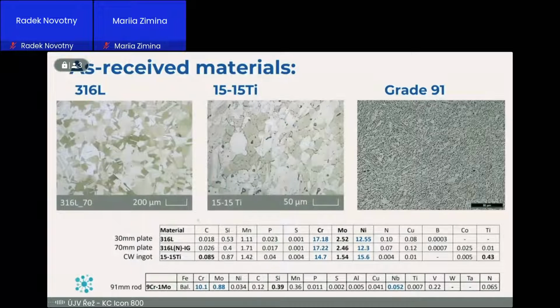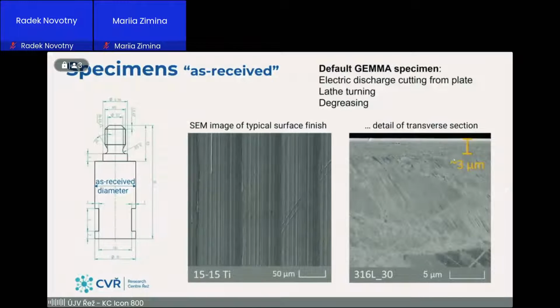There is titanium nitride, and the ferritic martensitic structure of this steel. So our specimens were cut from the plates by electric discharge, and the surface was finished by machining, that creates a very fine modified layer on the surface that became pretty important in our corrosion results. It was about 3 microns thick. You can see also some damage by machining. It's about 100 micrometers deep. So these are our specimens.